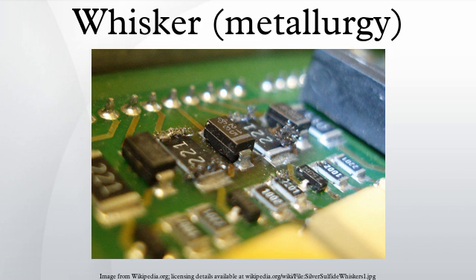Galaxy 4. The Galaxy 4 was a telecommunications satellite that was disabled and lost due to short circuits caused by tin whiskers in 1998. It was initially thought that space weather contributed to the failure, but later it was discovered that a conformal coating had been misapplied, allowing whiskers formed in the pure tin plating to find their way through a missing coating area, causing a failure of the main control computer. The manufacturer, Hughes, has moved to nickel plating, rather than tin, to reduce the risk of whisker growth. The trade-off has been an increase in weight, adding 100 pounds to 200 pounds per payload.